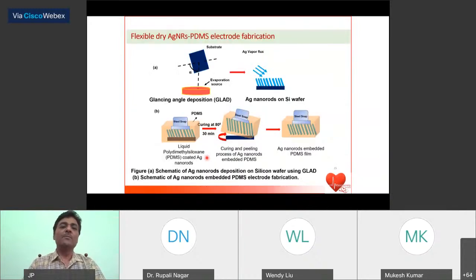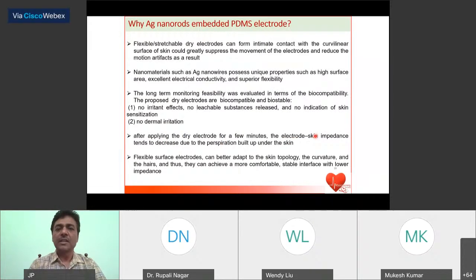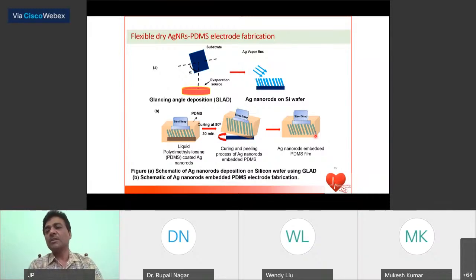So what we have done is we have fabricated, using glancing angle deposition, the silver nanorods, whose image I have shown before, and then we embedded these structures in PDMS, so that partly some of the nanowires are outside. This is not shown here, but some of the nanorods are coming out, and I'll show you the actual electrode also. So these structures are used as the ECG electrodes.